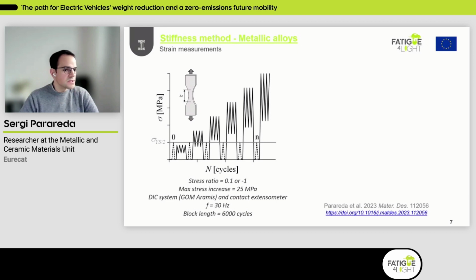In this case, we will start with the stiffness method, and in this method, the main point is to obtain the elastic response of the material at a given point, at different points of the test. And this test consists of applying different blocks with different stress amplitudes and increasing the stress amplitude between each one of these blocks. Here you can see the testing conditions that are the same conditions that can be used in the conventional SN curve.